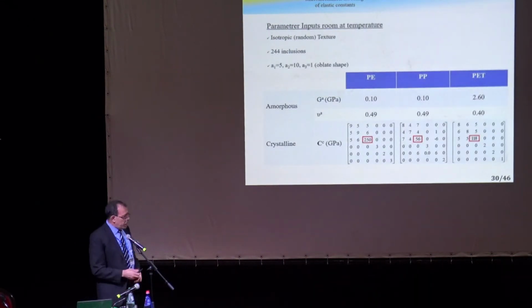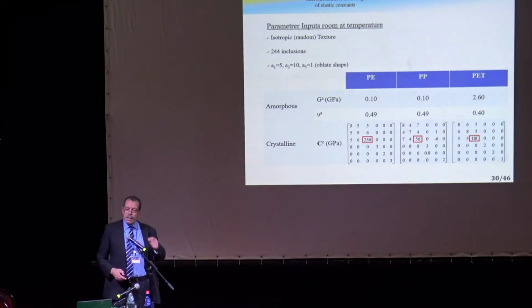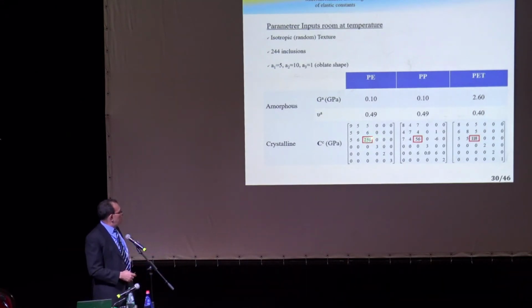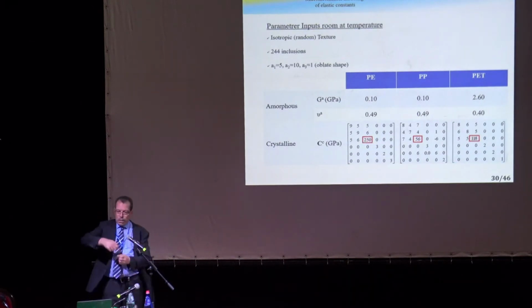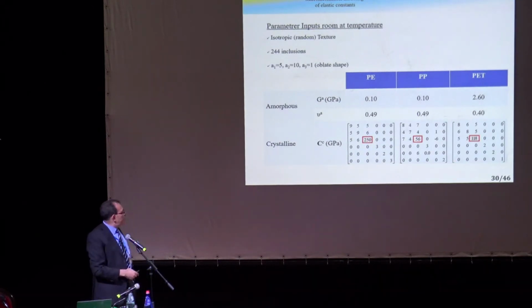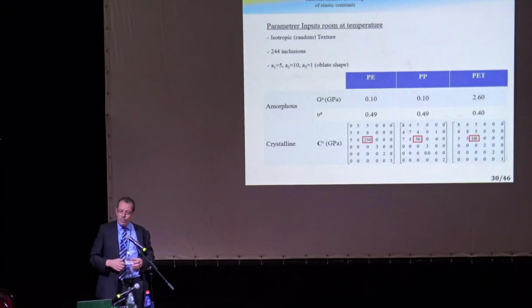All right, application to polyethylene, to PP, to PET, but I will focus only on PE. One thing I would like you to notice here is that the crystals are highly anisotropic in these materials. Look at polyethylene. This is the chain direction, covalent bonds, it's highly stiff. And if you look at the amorphous, the shear modulus of the amorphous is very, very low compared to this. So we have a high local anisotropy. And if you have oriented polyethylene, certainly you will have high anisotropy of your macroscopic material.